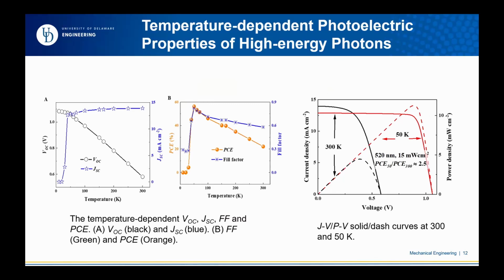Okay, so you can see there's a kind of turning point pretty much here. For this, as mentioned, we use a 520 nanometer laser. This turning point is actually the highest output power generated at that temperature, 50 Kelvin. If you simply compare the measurement at room temperature, 300 Kelvin, and at 50 Kelvin, you see the efficiency increased by 2.5 times.